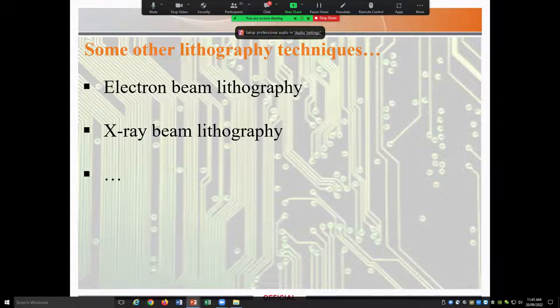Also, X-ray with wavelengths of 0.4 to 4 nanometer can be another source of radiation for lithography. And compared to EBL, it is much faster. But on the other hand, the masks that are used in this technique have to be made of low atomic number material, like diamond or beryllium, which is quite expensive.